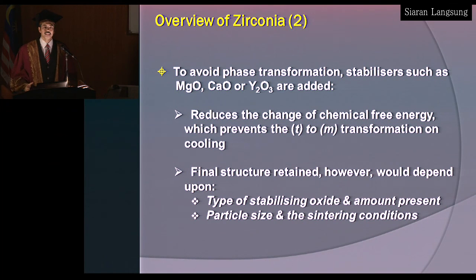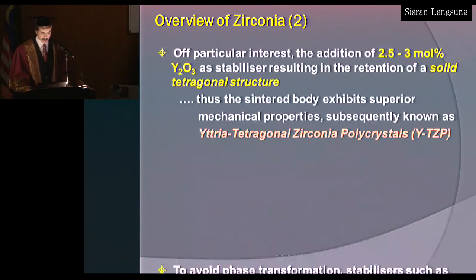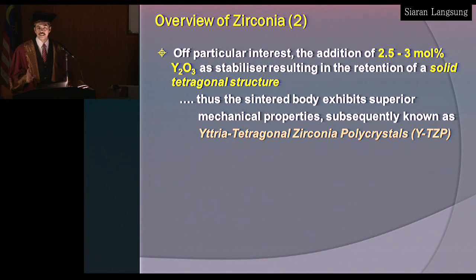Sintering is a term that is used in the ceramic field, whereby consolidation of the particles takes place. It's something like cooking, but because it is done at high temperature, the scientific term is called sintering. Now, of particular interest, the addition of 2.5 to 3 mole% yttrium oxide as stabilizer results in the retention of solid tetragonal structure at room temperature, and that's where the maximum or enhanced mechanical properties are retained. And this material is subsequently known as yttrium tetragonal zirconia polycrystal, or Y-TZP.